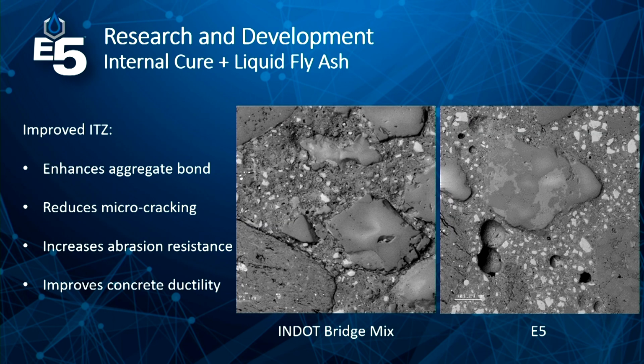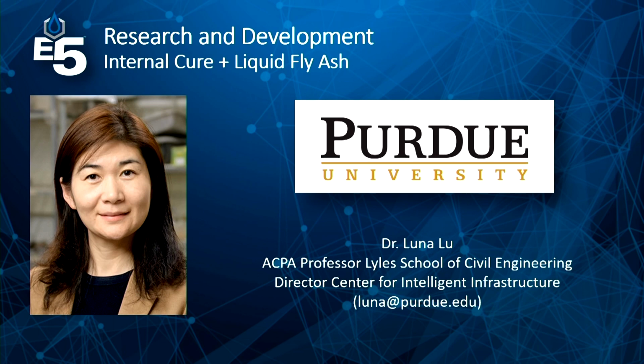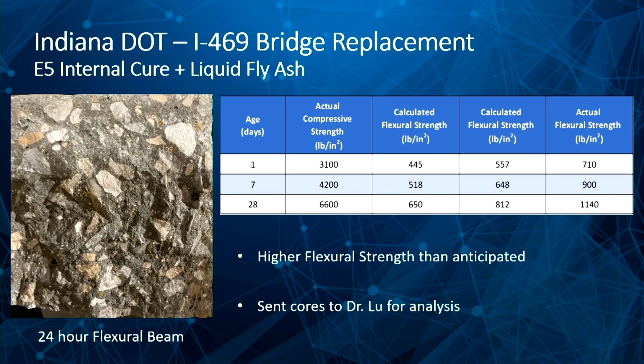When you improve the ITZ, you experience an enhanced aggregate bond. You reduce microcracking, you improve the resistance to abrasion, and you improve the concrete ductility. This concrete was able to bend more, and the aggregate didn't pull out before it failed. Forgot to say, that's a 1-day break with the E5. Look at all that aggregate fracture in there. Usually you see a lot of pull out at that break.